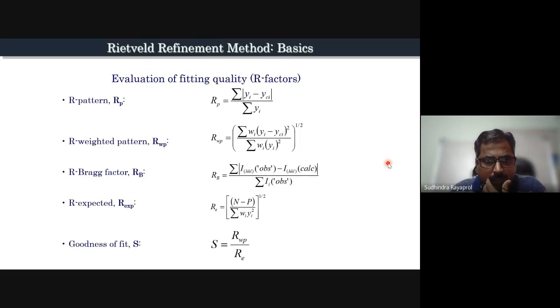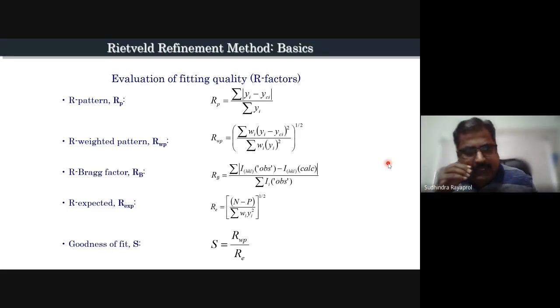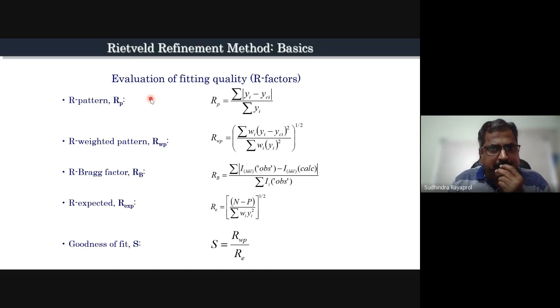Okay. Now, how do you evaluate the Rietveld refinements? There are different R values which are generated when you do the refinement. Something called Rp, or the profile R factor, which is basically the ratio of the difference of observed and calculated intensities to the observed intensity. Then you have what is called the weighted profile, Rwp. Rwp has some weightage provided. Basically, it works on the square of the differences between them. Then you have the Bragg factor, or RB value, which works on the integrated intensities of observed and calculated peaks.